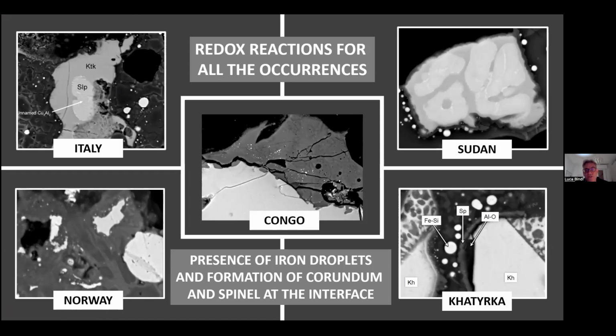So the first Khatyrka, then we have the Sudan spherule, then we have the Congo fragment, and then the Italian micrometeorite, and then two from Norway. So since the Khatyrka fragments are approximately 11, 12, we have approximately 20 fragments from different parts of the world containing copper aluminum alloys. And what is impressive, if you look at these images, you can see exactly the same thing at the interface between the copper aluminum alloys and the silicates.